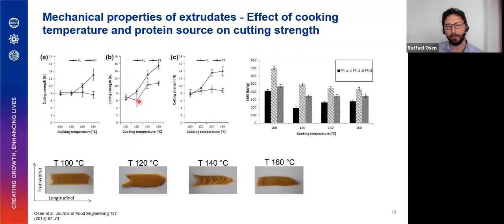And this was shown also in looking at the extrudates, showing a more ununiform fiber formation or ununiform structure. So it seems like the temperature was not enough. The thermal energy was not enough really to texturize these proteins into a fibrous texture.